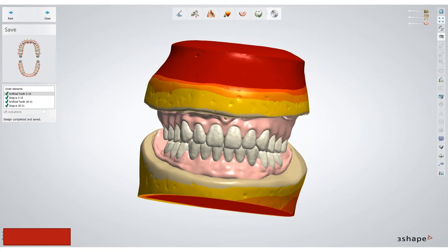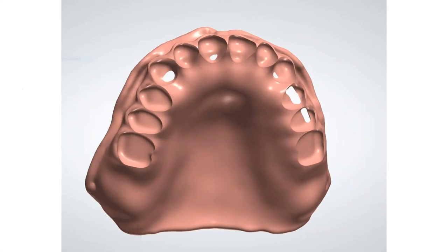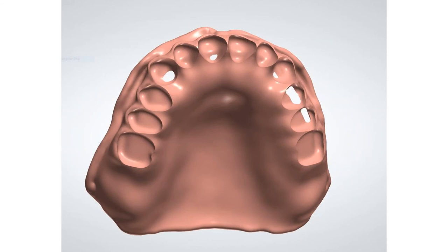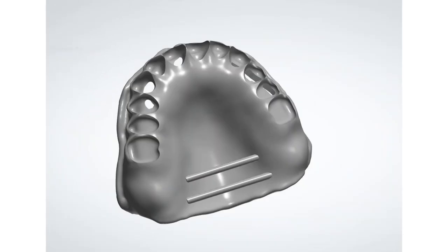There are quite a few positives here — you're using a regular denture tooth, getting all the aesthetics of it, and because it's digitally designed you get really good adaptation to the base plate. However, you need to consider case selection. For cases with recent extractions and a significant ridge — where you're going to end up with perforations through the base plate — that's fine if you're going the traditional processing route, but if you're planning on bonding teeth directly to the base plate that won't work. You can only bond those teeth to the base plate if there are no perforations of any kind.